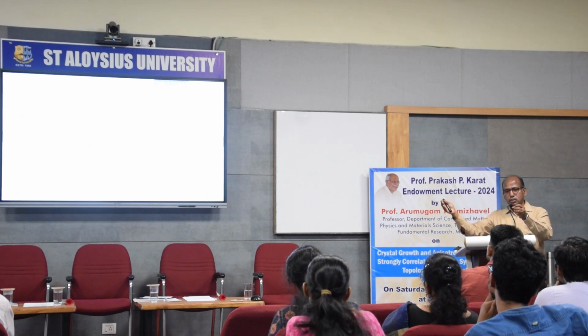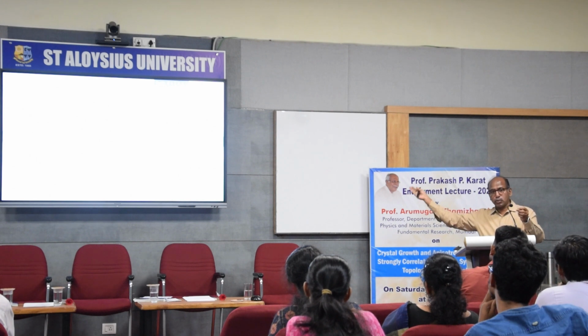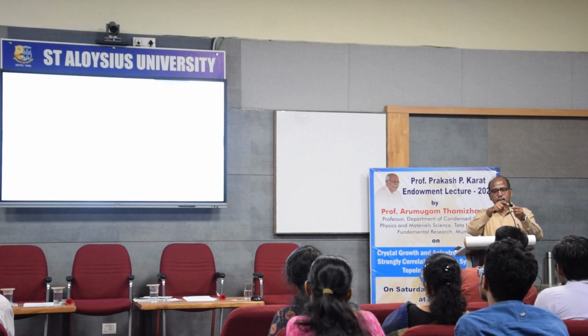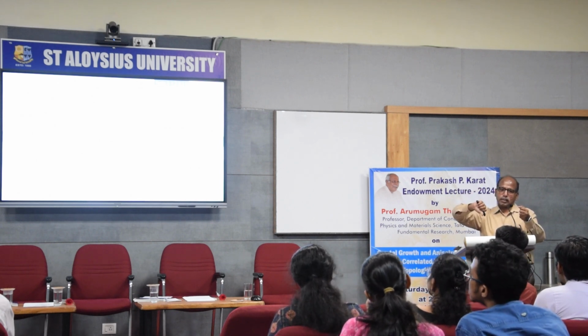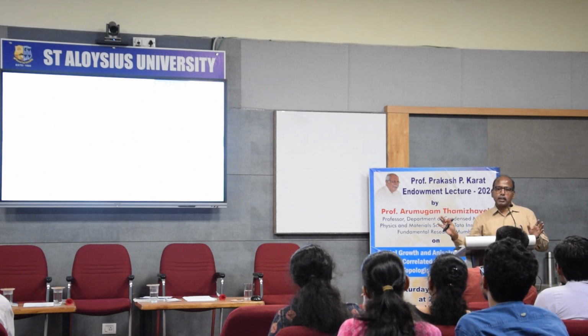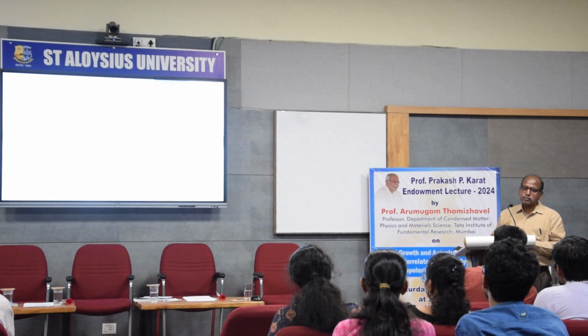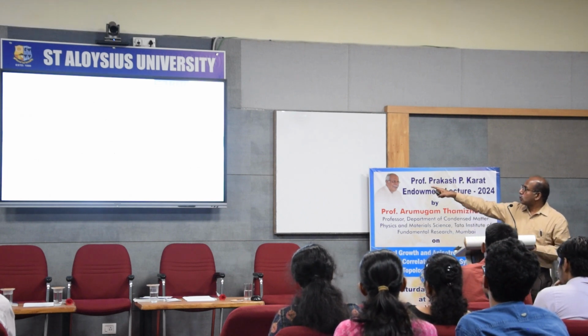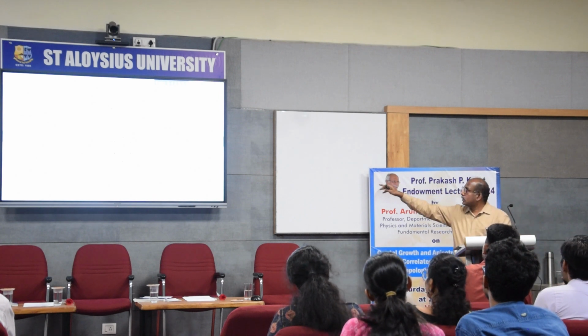And this exchange interaction, if it is positive, then this conduction electron passes the information via the other conduction electron to the other F electron, and we get ferromagnetic order. If this exchange interaction is negative, then it shows that we should follow this. So this is theoretically predicted, and it has been very well experimentally observed in most of the cases. Kondo effect is this one.